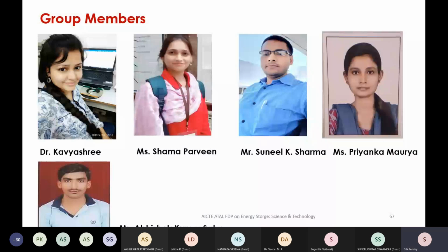So I thank these people for giving me the chance to learn about this supercapacitor, and without these students, I would not be able to understand what is going on on the experimental side. And really, they have done very hard work, because manually you are doing the dipping here for 20 seconds, then in another one for 10 seconds, then the third beaker for 20 seconds, and the fourth beaker again for 20 seconds. So manually you have to repeat it, and layer by layer, we are having 8 beakers, and in these 8 beakers you have to do it for 20 cycles, 30 cycles, or 40 and so on.